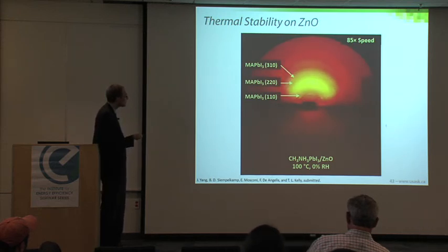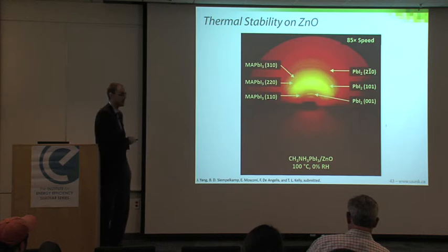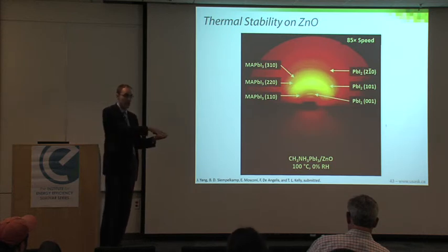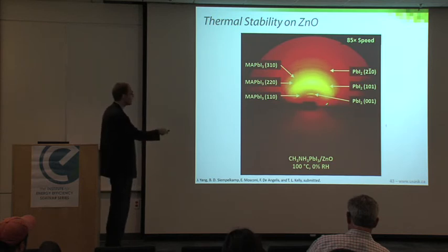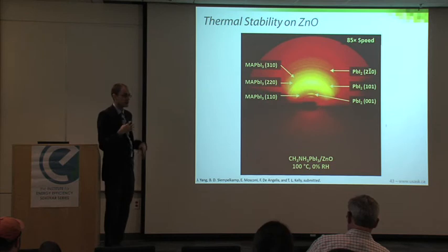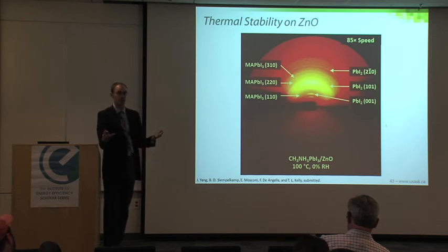You can watch as your perovskite disappears and your lead iodide grows in. And so it's a really smooth A to B transition. There's no intermediates. All of these line up really nicely for lead iodide. So it's perovskite to PbI2, starting material and product, and a very, very rapid decomposition process.